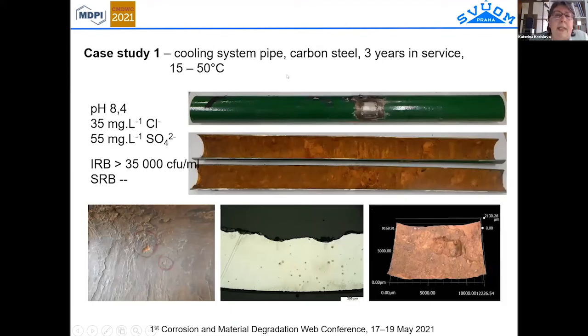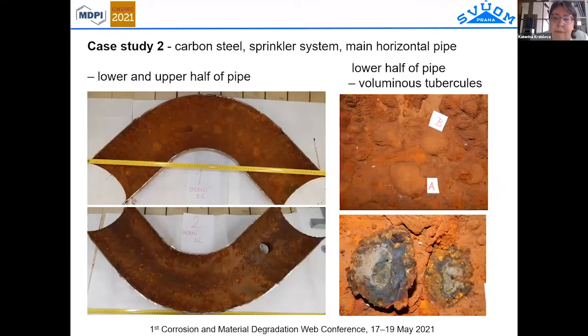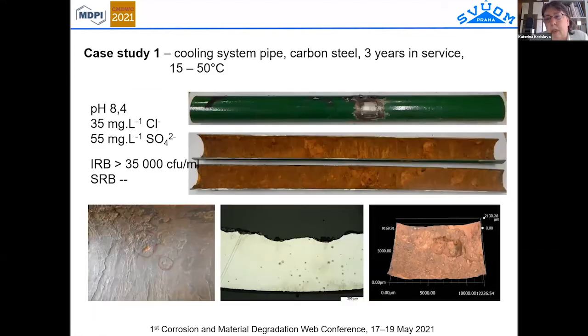This is the first case study. It was a pipe of carbon steel in a cooling water system after 3 years in service, and the information about the water shows that the concentrations are not so high, but the concentration of iron bacteria was relatively high. And you can see how the corroded surface looks. There is a lot of tubercles on the surface, and after cleaning the surface, relatively shallow pits are evident, which were full of sulfur.